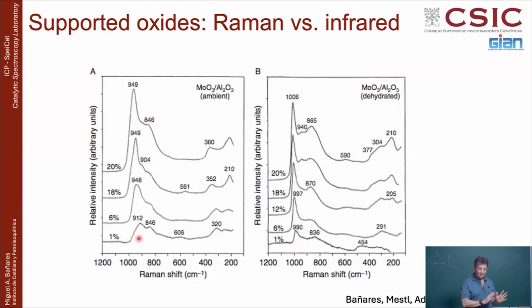But the nice thing at this moment for today's talk is mainly that you can see supported oxides very nicely. Here, this is ambient hydrated. This is dehydrated. This Raman band at about 990, 997, up to 1000 is associated with the dispersed molybdenum oxide. As you increase the coverage, you can see this molybdenum oxide is polymerized, and then you get this additional band over here about the bridging oxygens, molybdenum, oxygen, molybdenum. So you can tell the polymerization. And also this stretching mode at about 1000. It also has a bending mode at about 200 that you see over there.